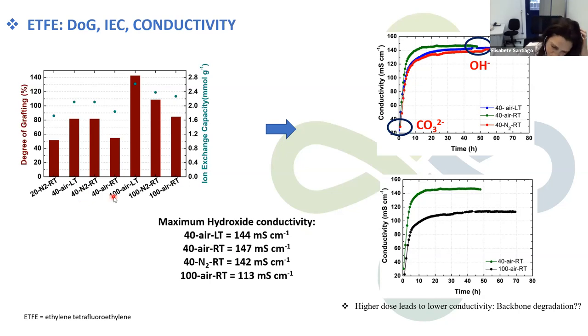Low temperature and nitrogen provide more stable radicals that can be used in the grafting process. So here I can see that you do not necessarily have a high degree of grafting and ion exchange capacity to have a high conductivity. Here I show you, for example, for 100 dose, you have achieved a conductivity of 113 millisiemens per centimeter. So higher doses lead to lower conductivity. But why is this? It's expected to be the opposite. But probably you have a backbone degradation.